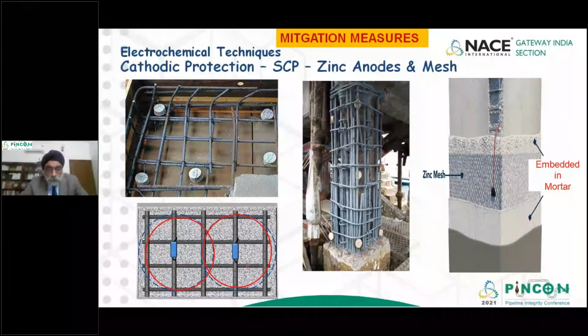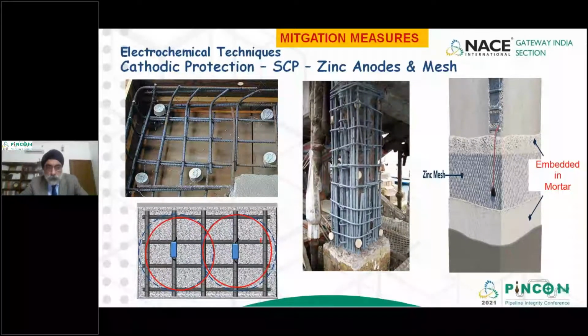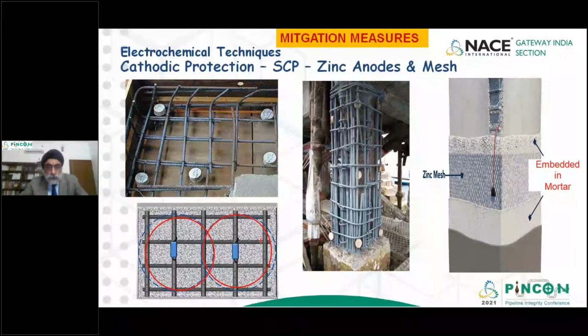Each anode has a limited area. It will not cover a very large area. It would typically cover 1.5 to 2 square meters. So if you are using a sacrificial system for protecting your structures, you need to be very clear that it will only protect about 1.5 to 2 meters square. So a large number of anodes have to be embedded in the concrete. The photograph shows, you can see in a small area, they have embedded almost 5 zinc anodes. There's also a solution where you put a zinc mesh around the pile cap or pile foundation if it is above ground, and then we put a concrete layer over it so that the zinc mesh gets embedded.